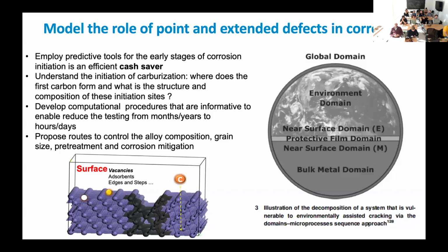So where does it start? Where do the first carbons form, and what is the structure and the composition of this initiation? And actually to develop computational procedures that are informative enough to enable reducing the testing from years to months. So here the purpose is really to try to see if we could propose some routes to control the alloy composition, grain size, pre-treatment, and corrosion mitigation. It's a very big scope, and you see that it goes into different domains that are related to the environment, the near surface, the protective film, the surface, and then the bulk metal. And each of these environments needs to be treated carefully, and sometimes with different computational techniques.